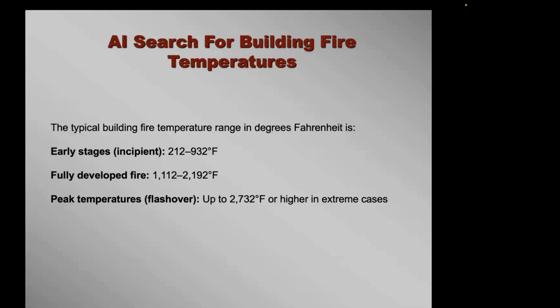So here's the concerning part. I did an AI search for building fire temperatures. Your early stage temperatures are 212 to 932 degrees F. A fully developed fire is 1,112 to 2,192 F. Peak temperature is a little over 2700 degrees. These products are going to melt in a building fire, and you're going to have rainscreen panels falling off the building.